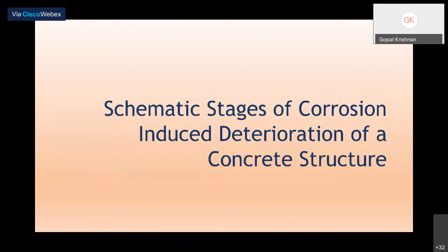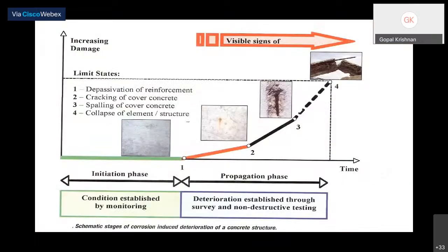I'm going to show one schematic of the stages of corrosion-induced deterioration of concrete structures. There we can explain whatever we discussed. So here we can see that there are 4 stages given, based on the exposure condition, of structure deterioration. What we said, different structures have different service lives, but most of the structures do not attain their service life because of poor maintenance. So here, in spite of all our precautions and preventions, concrete deteriorates in severe and extremely severe exposure conditions. So the root cause of deterioration needs to be ascertained.